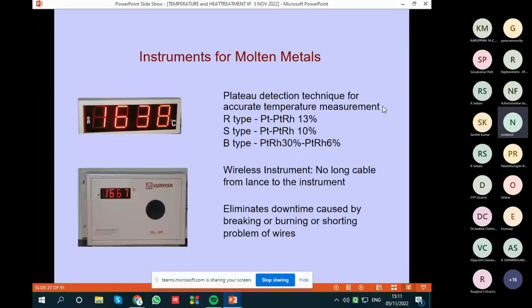What is the instrument? When you dip in molten metal, there is slag. So when you want to take the measurement and take a tip out, what happens if the slag is hotter? Then the slag is hotter than the molten metal, and you may get a very incorrect temperature.